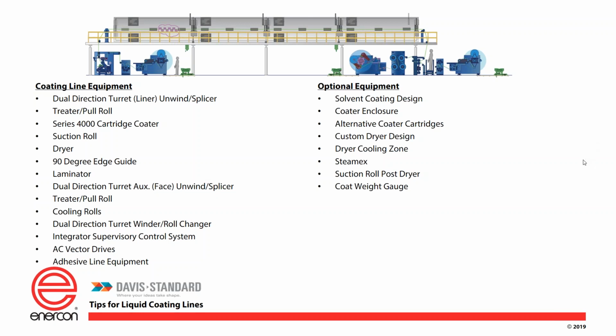That helps pull the web through the coater, even though now I'm changing the weight of that web, so my tension changes. So I have to have a new piece upstairs, which we use a vacuum roll here, a suction roll, to create that. It also controls the tension through this dryer. We're showing you here a flotation dryer, flat, 4 zones, okay? When you exit a dryer, you have camber in most webs, which means if you roll this web out on the floor, you'll see like a banana shape to it. So as you relax it with the lower tension in the dryer, some of this camber can actually affect the alignment of the web in the dryer.